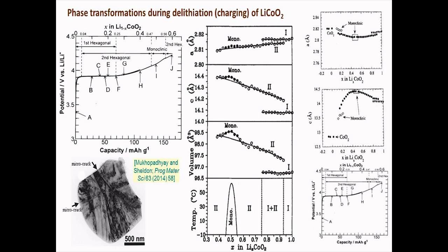Some of the things which the electrode materials undergo during the progress of lithiation, delithiation: it is anyway a foreign ion going into a host lattice. So there will be transformations, and like in most materials, there will be a lot of phase transformations, as we say, first order phase transformations. Lithium cobalt oxide, the workhorse cathode, goes from hexagonal to monoclinic phase during the progress of lithiation, and that will lead to a jump in the lattice parameter, which is not good for the material because it can lead to a lot of defect substructures and also cracking. Slowly I'm moving into the stress aspect.